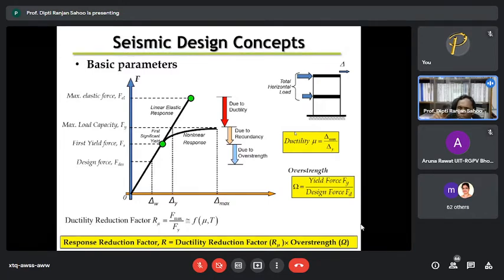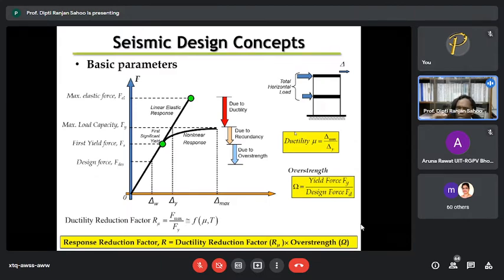The second, the same material, if I use it in a beam and I test that beam, what you will find is that your beam design is based on the yield point. But due to material strain hardening, your beam would take a higher load than it was designed for, because your design is always limited by the yield point, but your material has strain hardening and then the ultimate point before it goes to collapse. So you have inherent overstrength due to the strain hardening, and at the same time, a material of 250 grade steel, when you actually test in the lab, you will always get 260, 270 as the actual yield point. So you have overstrength in the material, you have overstrength due to strain hardening, and your design is not based on the ultimate, it is based on the yield.